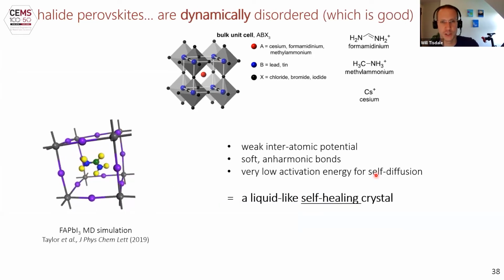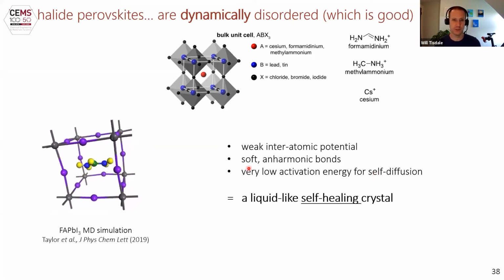And so the picture that emerges is this highly dynamic material at room temperature, weak interatomic potentials, soft anharmonic bonds, a very low activation energy for self-diffusion, which presents a picture of something kind of liquid-like. It is very much a solid, but it's a very, very dynamic solid that can very easily heal defects within the crystal. This is a molecular dynamics simulation of formamidinium lead iodide at room temperature. The magnitude of these vibrations are completely unlike you would see in silicon, for instance, at the same temperature.